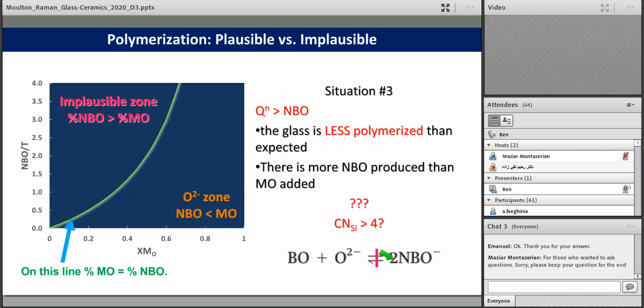For most silicate glasses at ambient conditions, there are basically no compositions, with one or two very specific exceptions, where the coordination of silicon changes to anything other than 4. So silicon must be 4, and you can say that this is indeed impossible at ambient conditions, but that may not be true at higher pressures.